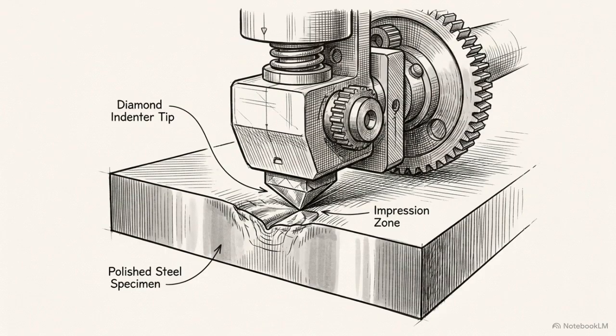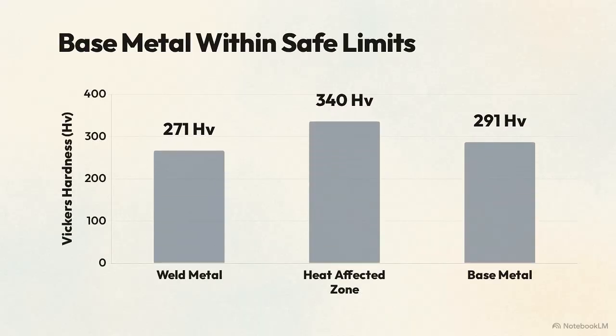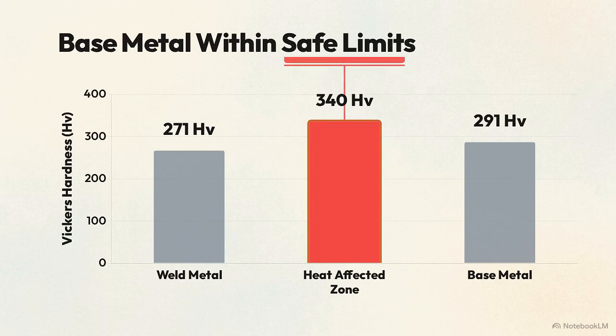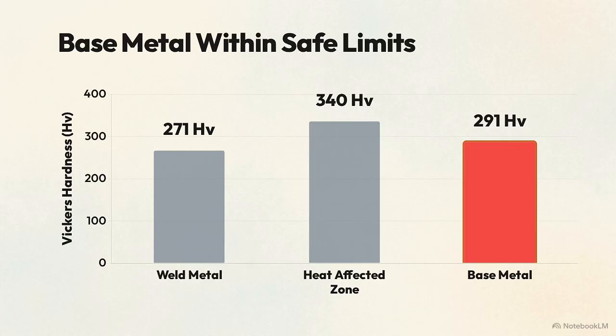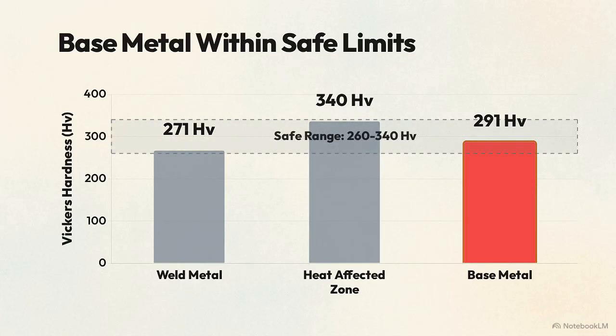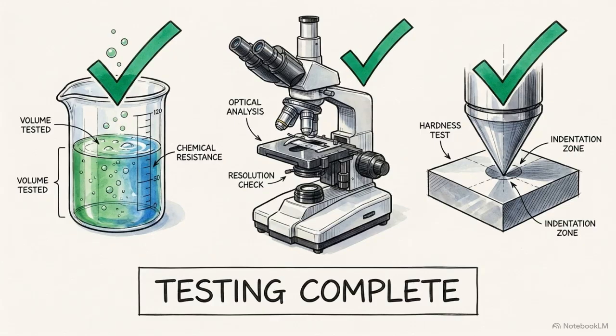We also have to confirm that the welding process did not inadvertently create a brittle or compromised zone, which requires a cross-weld hardness trace. This graph plots Vickers hardness across the three primary zones. As expected, the untempered bainite inside the heat-affected zone registers as the hardest region. Conversely, the unaffected base metal registers at 291 on the Vickers scale, placing it within safe tolerances. The chemistry is exact, the microstructure is correct, and the hardness profile is within specification. Material defect is eliminated as the cause.